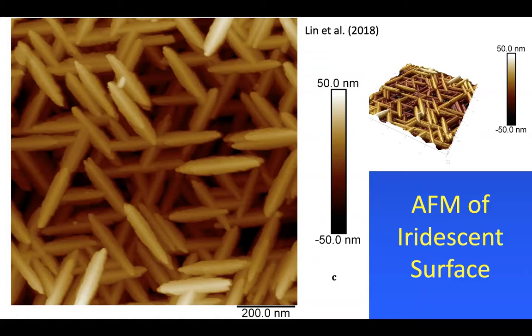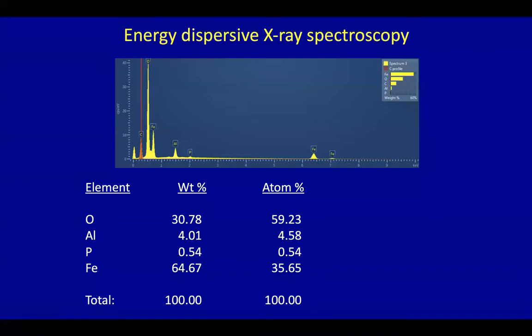And so what you see here are these little spindles, again, oriented at 120 degrees from each other. The lengths of the spindles are usually on the order of 200 to 400 nanometers. The width is much less, about 30 to 40 nanometers in size. So we did our own energy dispersive spectroscopy, and we did indeed find evidence for the aluminum and phosphorus that George and Chima had described earlier.